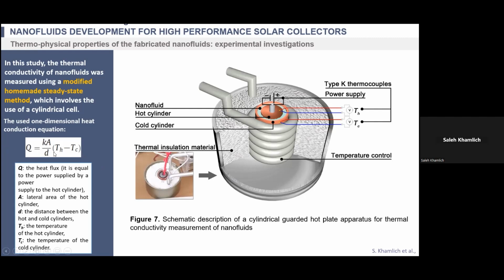So through Fourier's law, it's very simple, as you can see. If you apply power to the inner cylinder, you create heat on the surface of this cylinder, which leads to heat flux through the nanofluid in the annular space. Once we heat the surface of this cylinder, the heat will go through the nanofluid to the cold cylinder. By using this equation, which shows the area of the inner cylinder, the distance between the cylinders, and the difference in temperature between the hot and cold cylinders, you can extract the thermal conductivity.